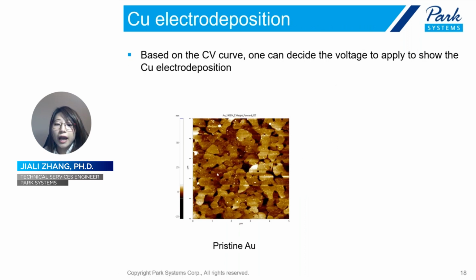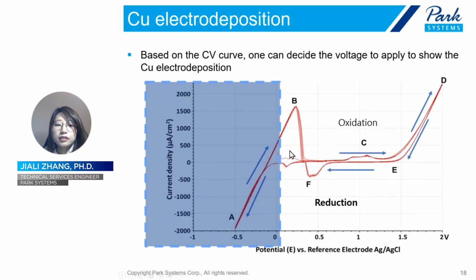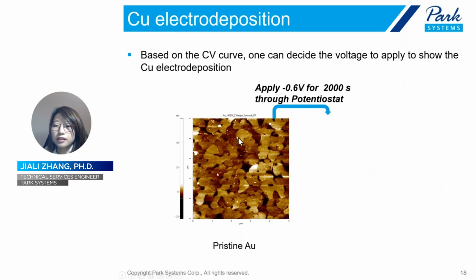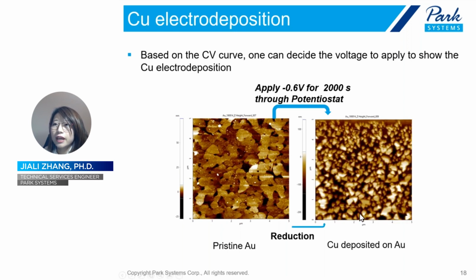So now we can switch to the actual AFM result. This is a bare gold surface with visible terraces, imaged by AFM in liquid before the CV sweep. Then based on the CV curve generated just now, one can find the threshold potential for copper deposition, and we will apply negative 0.6 volts continuously. After that, we take the AFM image of the same area. You can see in this AFM image, scanning from top to down, with the time increase, the deposited copper clusters grow from smaller size to bigger size. So this means that the deposition rate is increased with time.